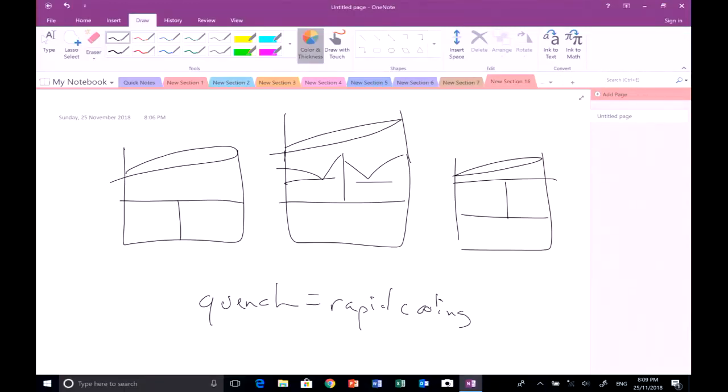Just Michael Ferry does about 1 million degrees a second. It is really fast. But he's trying to prevent metals from recrystallizing. They diffuse very quickly, so they've got to cool really quickly. The ceramics, they're much slower. 30 seconds was good enough for me. So I quenched everything, and that's what you try to do, to freeze in the high temperature phases, and that's usually considered good. Usually gives you a picture of what's happening, an accurate one. Okay. But we have these complications, and these are a couple of examples I haven't shown you.